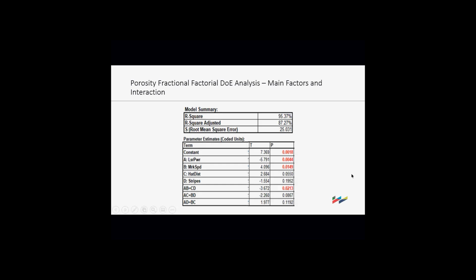Okay? And so we did a porosity fractional factorial. And so with this one, again, the constant is significant. Laser power, scan speed we've seen before. We have an interaction there. But because of the fractional factorial, I can't tell the difference between an AB or a CD. So they're connected together. They're mixed in. But if I look at AB, laser power and scan speed, I'll put any money on that's the interaction I'm actually having, is AB. Because many factors that are significant, most likely the interaction is too. But you don't know for sure, but most likely it is.